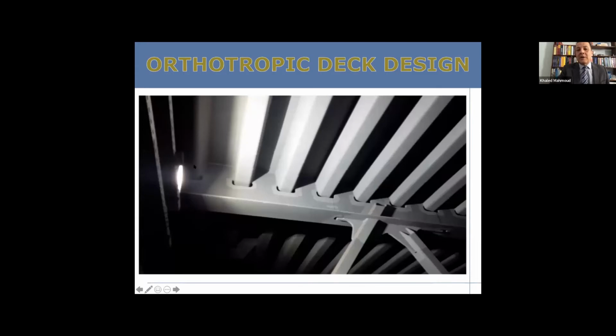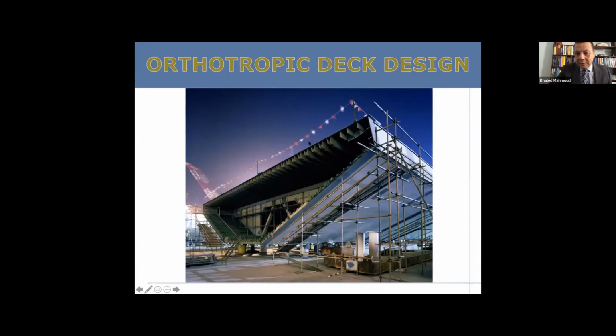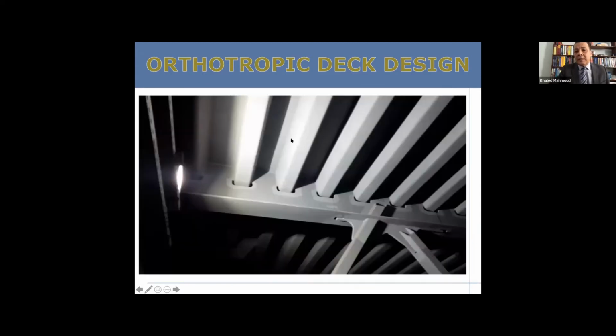Over here, you see these are U-ribs at the top, and there's a thin steel plate, and here at the bottom of the bridge deck, you see the U-ribs with the deck plate on top, and this is a cross beam. Cracks can develop either in the deck plate itself, or in the longitudinal weld between the rib and the deck plate. They can develop at the splices where you connect the U-ribs, or at the connection of the U-rib to the cross beam.